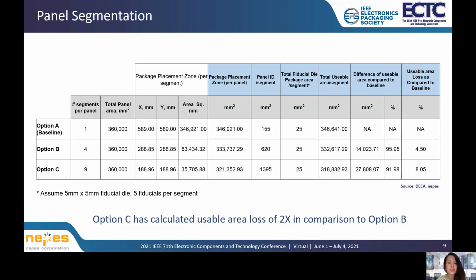Total usable area loss was calculated by subtracting the sum of package placement, keep-out zone, fiducial die, and package ID from total panel area. In this example, option C has calculated usable area loss of 2 times more in comparison to option B. As we get into larger package sizes or multi-die packaging for panel level packaging, the positive impact of 4 versus 9 segments on a 600 mm panel would be larger due to keep-out zone and placement of the die to maximize usable panel space.